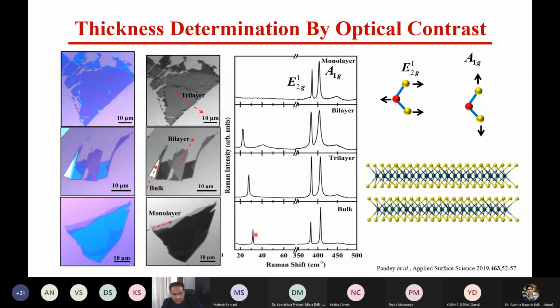And you can see there is another Raman peak very close to the laser line, okay, which is present in the bilayer and it is missing in the monolayer region, okay. So this particular peak is related to the interlayer breathing mode of the MoS2, and this peak is missing in the monolayer because there is no interlayer breathing mode here, okay.